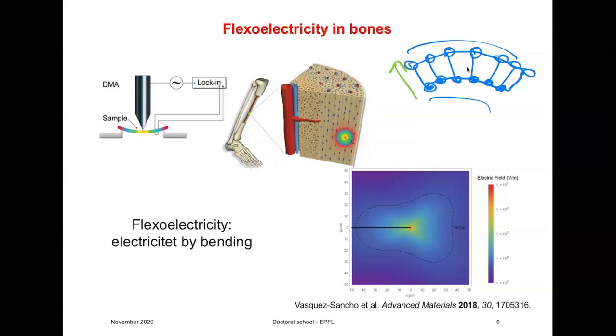Across this material, and on the other hand, if you have inhomogeneous electric field in the material, it would locally polarize material differently in different parts of the material, and then you would have bending of the material. So there is a direct and converse flexoelectric effect. Why don't we talk much about that? Well, the flexoelectric effect is closely related to the strain gradient, and that strain gradient in normal solid bodies cannot be very large, so flexoelectric effect is actually relatively small, orders of magnitude smaller than piezoelectric effect. However, now with this technology where we can make very thin films, the strains can be huge just from the top to the bottom of the film. Strains can be huge, and therefore on a nano scale, flexoelectric can be, or micro scale, flexoelectric effect can be very large.